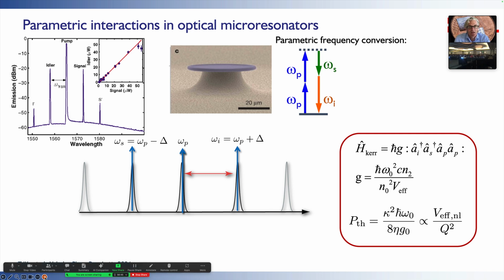This is based on a process called parametric interactions, whereby when you pump one of these microresonators, you generate sidebands due to the Kerr nonlinearity of the material itself. So it's a parametric oscillator, and typically this is distinct compared to a laser. The threshold power of parametric oscillation scales inversely quadratically with the quality factor. So the higher the Q of the optical resonator, the lower the threshold will become. This is different than a laser, where the threshold would have a 1/Q dependence. So having high Q can bring down the threshold dramatically, even for very faint nonlinear effects like these parametric interactions.